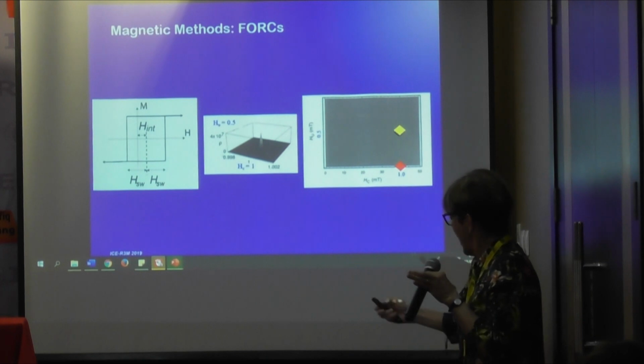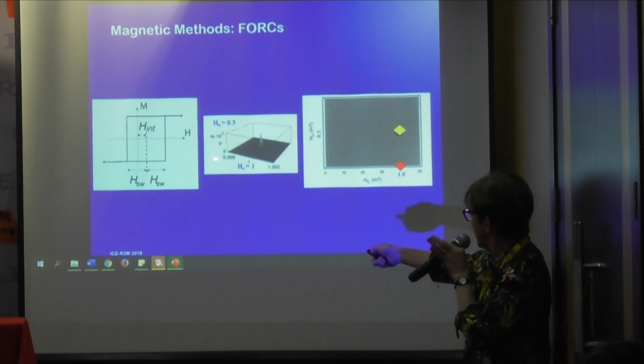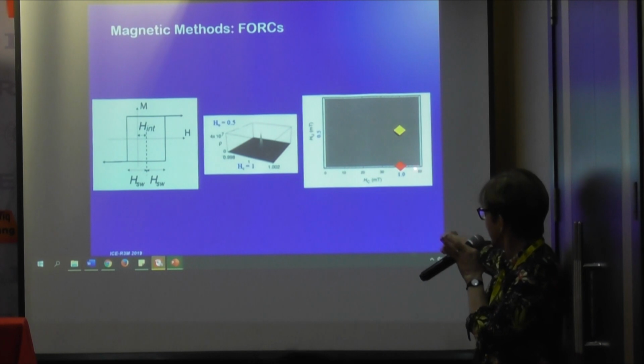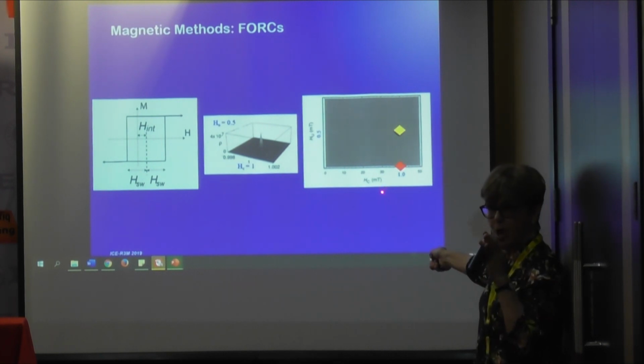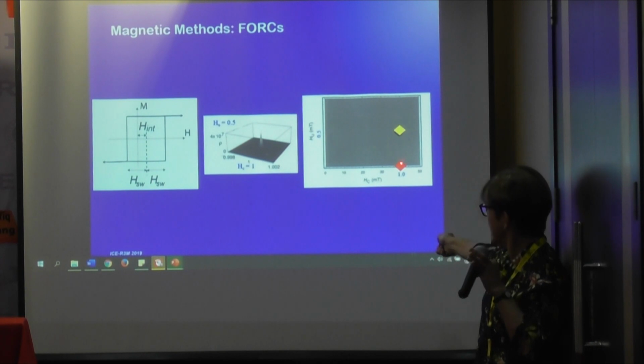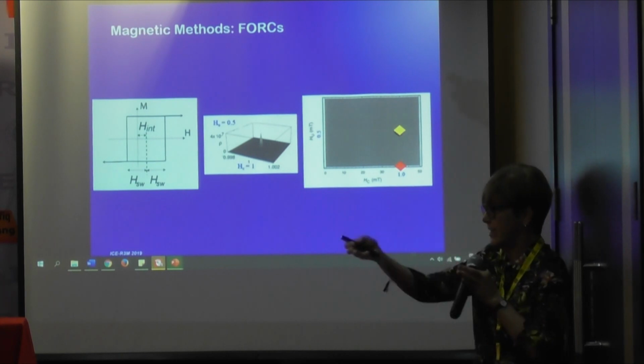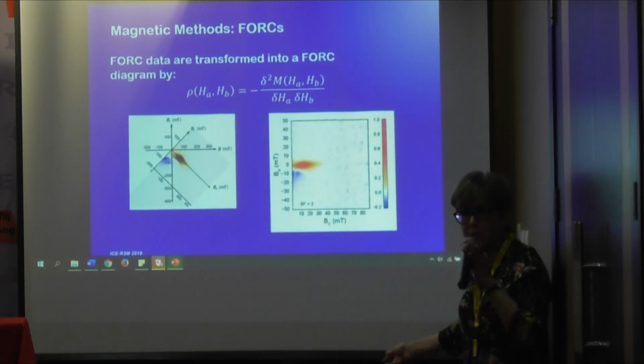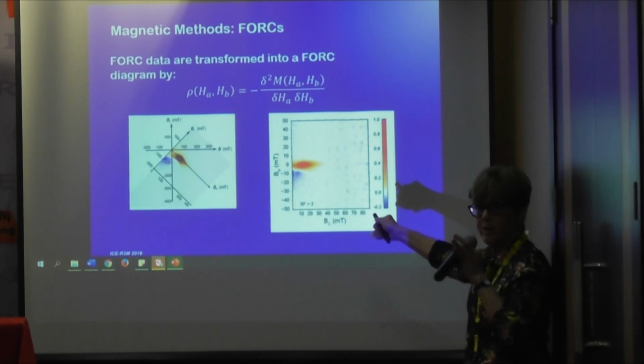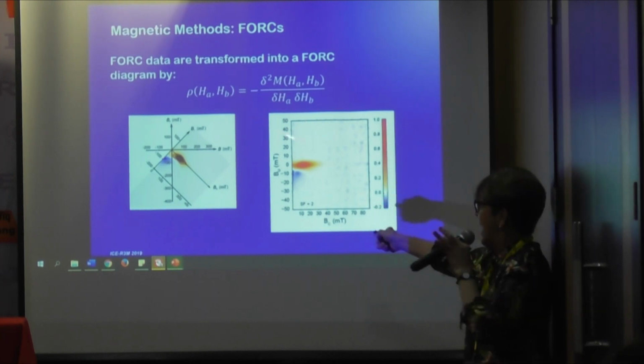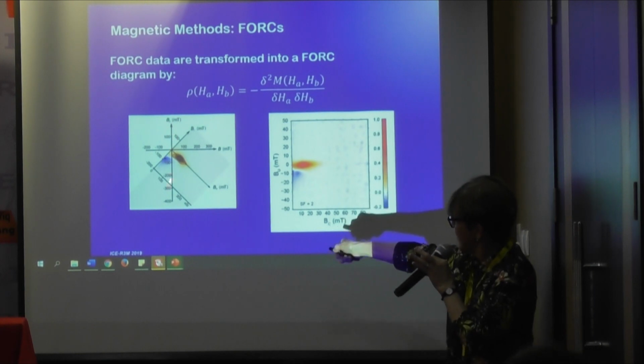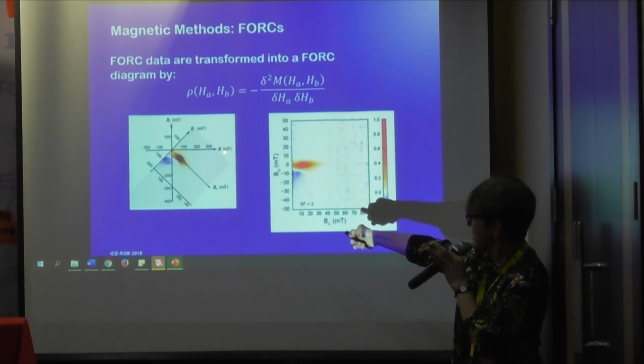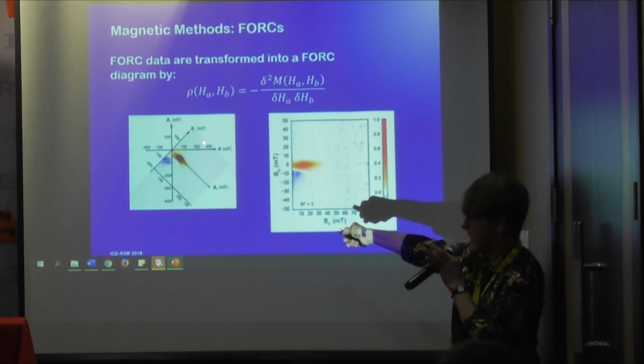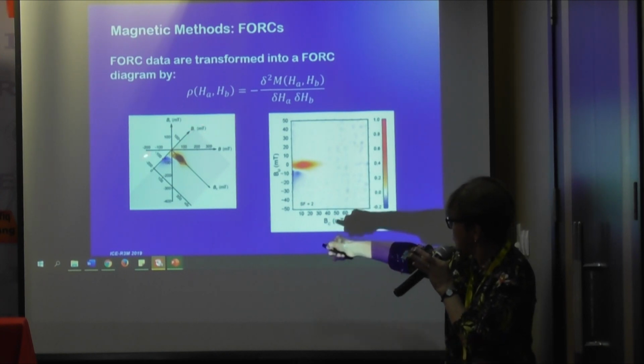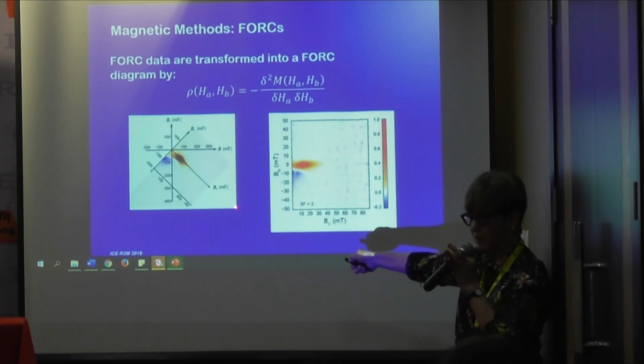And that would look like this on a FORC diagram. I have my coercivity here. It's 1 in both cases, but in one case, the interaction field is 0, and in the other case, the interaction field is 0.5. In principle, what I'm going to be doing is a second order derivative because I'm looking at the change of slope. This is my reverse field axis, this is my applied field axis, and I'm going to translate this with the second derivative into the interaction field on this axis and the coercivity on this axis.